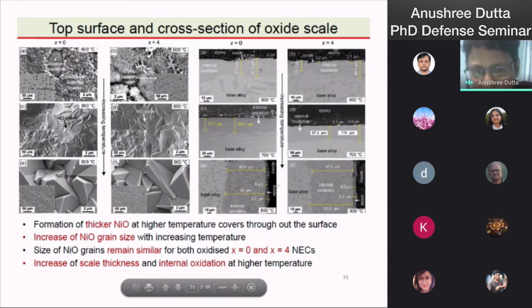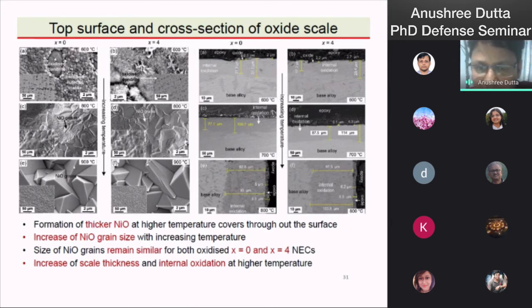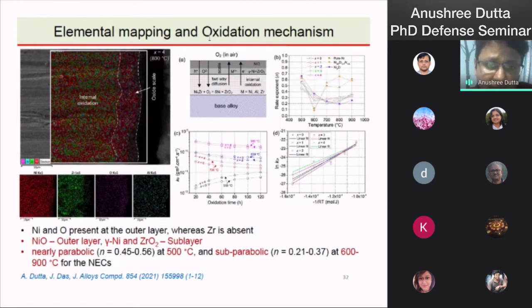Here, in the cross section of the oxide scale, we can find three distinct layers: the unaffected base alloy, the internal oxidation region, and the oxide scale, where the thickness of the oxide scale and the internal oxidation region increases with increase of temperature. The elemental mapping shows that the oxide scale is mainly composed of nickel and oxygen, where this is a zirconium depleted region, and the zirconium is found below this region. So it can be said that the zirconium oxide is formed below the NiO layer.